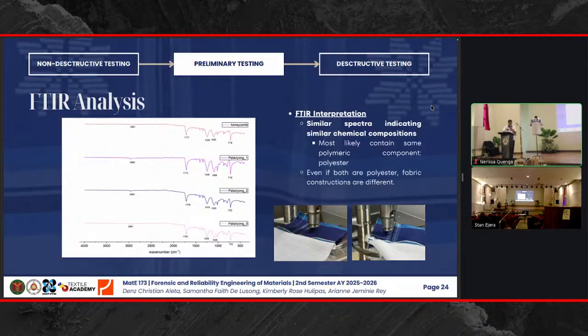So, indicating ito na meron daw siyang ester stretching, which is actually the diagnostic peak for polyester. And then additional peaks naman at 1240 to 1270 and 1090 to 1100, indicating aromatic ester and C-O stretching vibrations, respectively, further confirming the presence of polyester. And then may notable peak tayo at 720, the aromatic C-H bending peak, and small absorption bands around 2900, which may be associated with fabric treatments such as dyeing or the incorporation of biocolorants. And then overall, the FTIR results confirm that both fabrics are composed primarily of polyester. Therefore, it can be inferred that the observed failure is unlikely to have originated from differences in fabric composition.